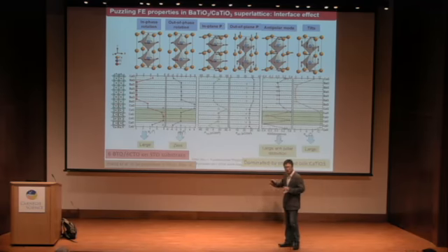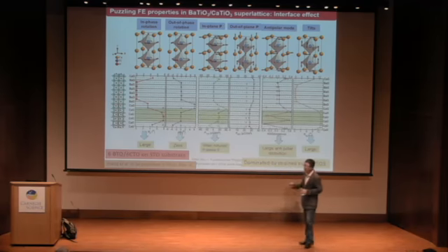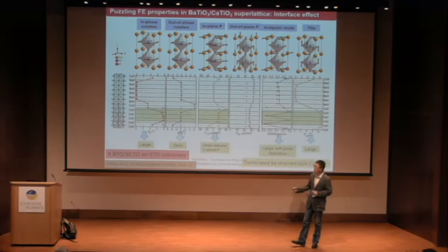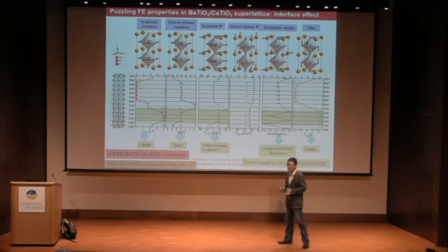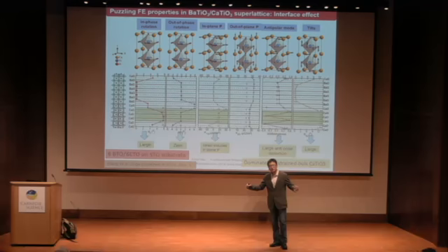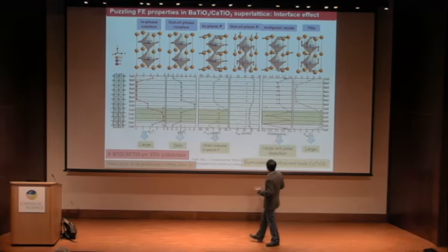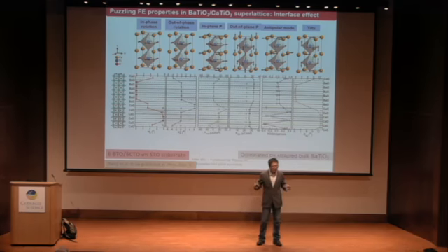So this is bulk effect. There is also an in-plane polarization, coming from strain-induced effect. This was also published by Karen Rabe and her student. If you apply an epitaxial strain, then you will see a polarization develop in the 110 direction. So this is the bulk region of calcium titanate.